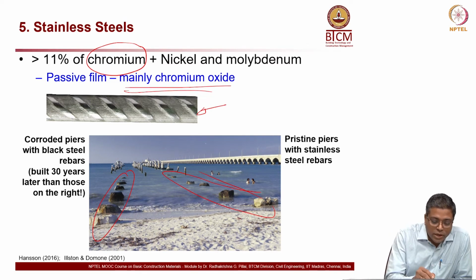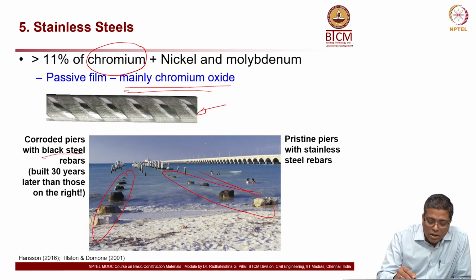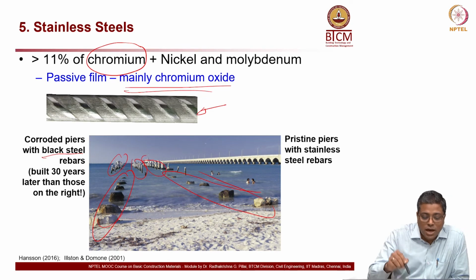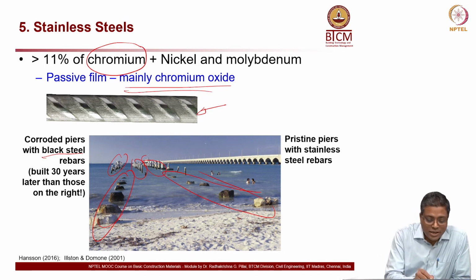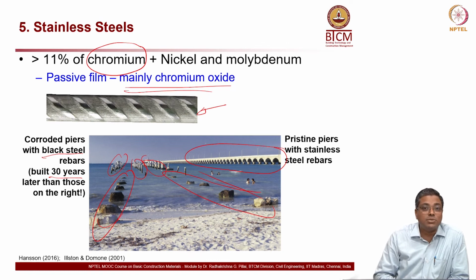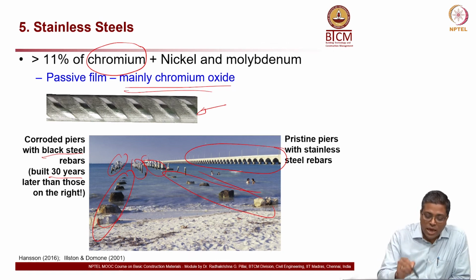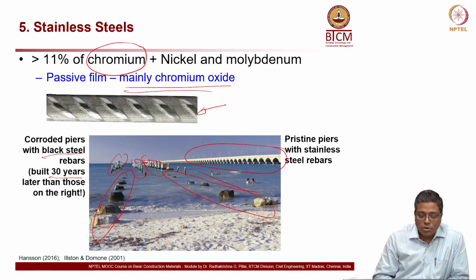So, corroded piers with black steel. Black steel is the conventional steel rebar. These piers are all corroded, but this bridge was constructed 30 years later than those on the right. This is a bridge with stainless steel rebar. In the same marine environment, a chloride-rich seawater environment, when you use stainless steel, it does not corrode.